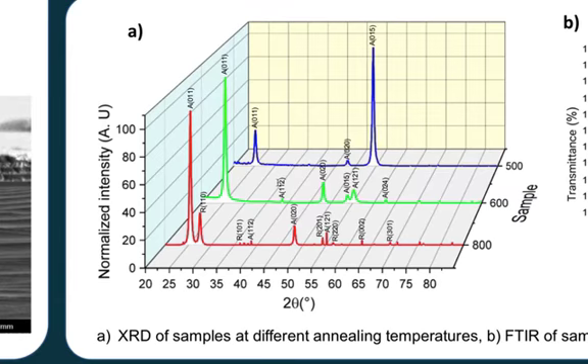The XRD pattern showed that there is formation of the anatase crystalline phase for titanium dioxide and amorphous silicon dioxide. At annealing temperatures greater than 600 degrees, the formation of the rutile phase for titanium dioxide can be observed. The formation is not complete, so we have both phases, but at temperatures around 800 degrees this makes it more difficult to adjust the thickness with respect to the refractive index, since the rutile phase has a higher refractive index.